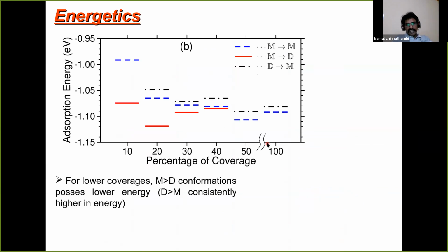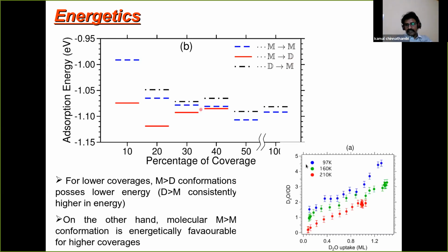The first most important thing is that whenever you have the dissociated molecule as an acceptor, we always see that at lower coverage it is lower in energy. This is again consistent with our experimental results, where we see that when you go to lower coverages, the dissociation is more. So somehow we could relate the lower binding energy of the dissociated molecule as an acceptor with the experimental results. That is a very good connection, the first we got between the experiment and theory.